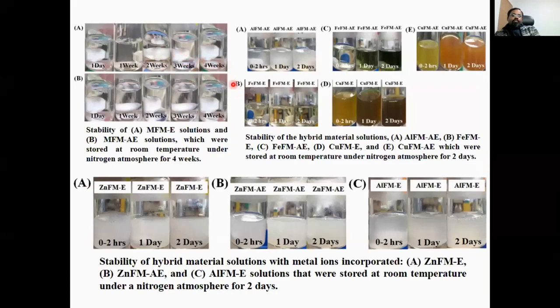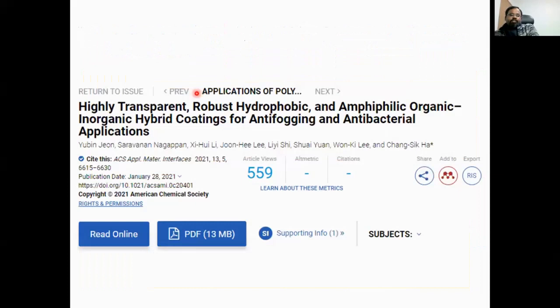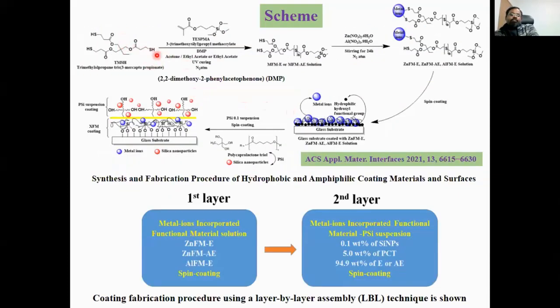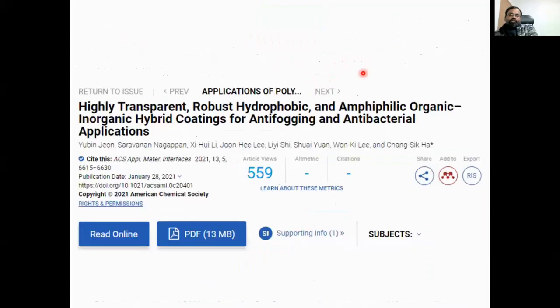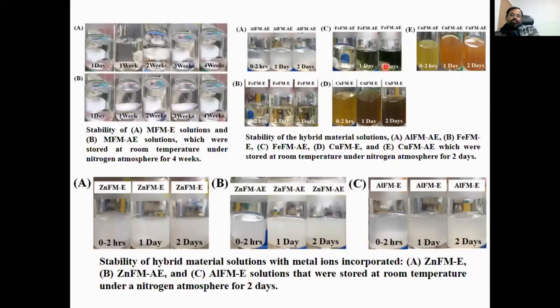After loading some metal, the metal-ligand coordination happens, so the reaction is much faster. In this case, we can use copper, gold, and other transition metals also. But because these mercapto functional groups are highly reactive with gold, mercury, silver, and other metals, and due to cost, to make low cost materials, we focused on zinc, aluminium, and other metals. First we tried iron, as you developed previously.